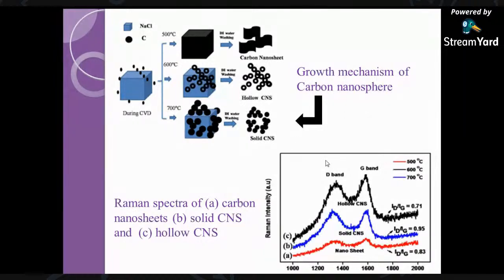When we study the Raman spectroscopy for the crystalline nature, we can see that the ID by IG ratio changes with temperature. The lower temperature has a 0.83 ID by IG ratio, then 600 gives you 0.71, and 700 gives you 0.95. So you can see that you have more defects at higher temperature, because of deposition of amorphous carbon over these nanospheres.